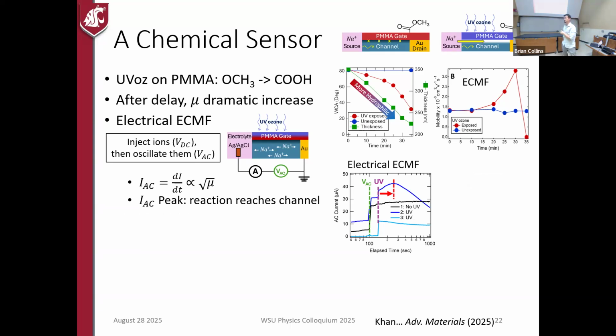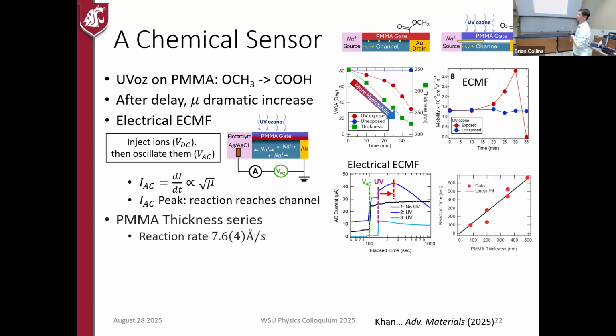So you notice that there's a time delay though. So why didn't it happen right away? Well, this is an oxygen reaction, so it's got to make its way through the depth of the PMMA layer, right? So there's some amount of time it takes for that to happen and reach the bottom of the PMMA, turning it hydrophilic, and then turning on this channel. And so, well, then if you have different thicknesses of PMMA, there should be different delay times, right? And that's exactly what we see.